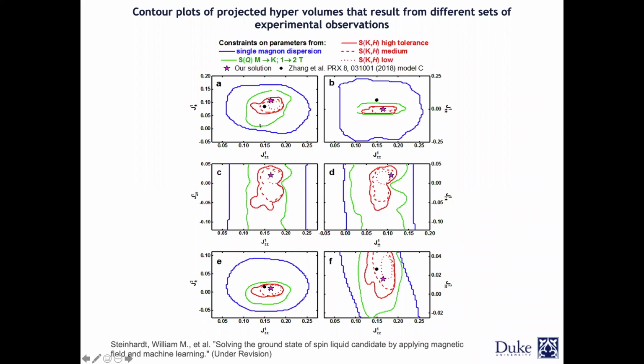So then they started to say, okay, let's look to see there is this change from M point to K point, and whatever model that we are going to discuss in here, practically all the parameters that are within this circle are going to be okay in the case of single magnon dispersion. But also this change in the M and K needs to be addressed. So then they started to restrict the parameters even more, and then they picked the solution based on where this is going to be.